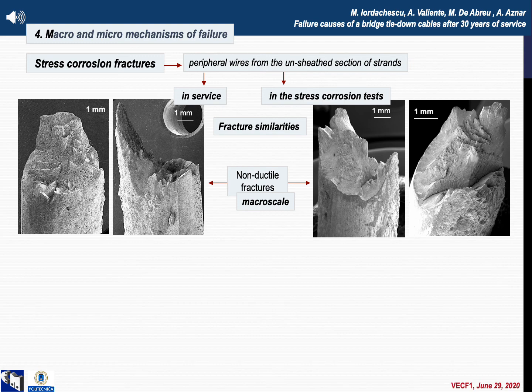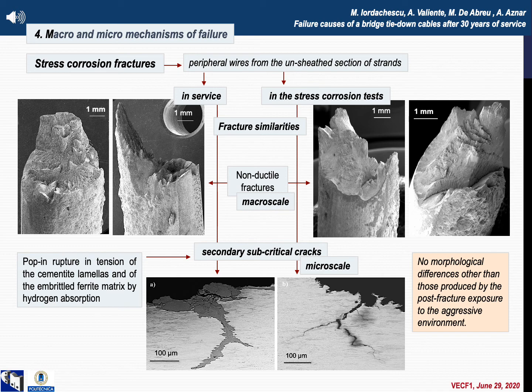The microscopic images show the secondary cracks found in the longitudinal sections of the wires close to their fracture surfaces. The first was broken in service, the latter in the stress corrosion constant load test. In both cases, these cracking processes were interrupted by the wire's failure in a similar process. The cracking micromechanism consisted in the pop-in rupture in tension of the cementite lamellas and of the ferrite matrix by hydrogen uptake. The only significant difference between the two secondary cracks is due to the time that they have been exposed to the aggressive environment, the service crack faces being covered by corrosion products formed after the wire breaking.